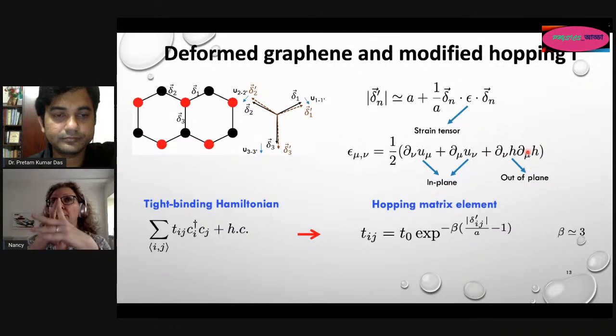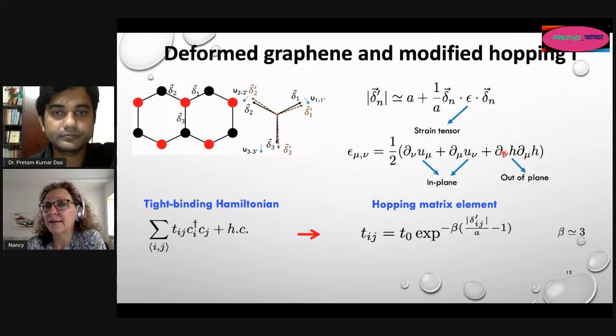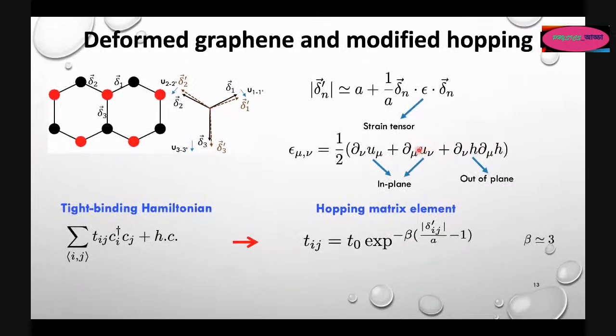The atoms can get a position out of plane, and how the position changes out of plane is described by this term in the strain tensor, in elasticity theory. The difference between these two first terms and this one, as you can see, is that this is nonlinear. This is a quadratic term in the positions of the atoms, while these two are linear in the positions of the atoms. That makes a big difference because this introduces nonlinear effects into the theory.